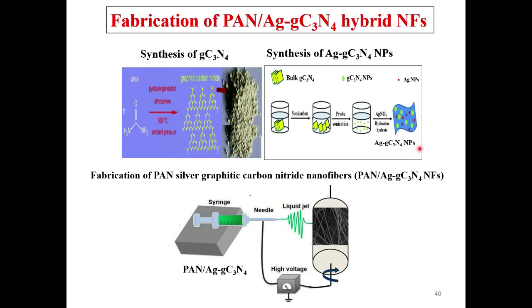The solution of AgGC3N4 nanoparticles is incorporated into the viscous solution of polyacrylonitrile polymer, and then we put the solution into the syringe, and we draw the fiber with the help of the electrospinning technique. This is the fiber which we have drawn with the help of electrospinning.